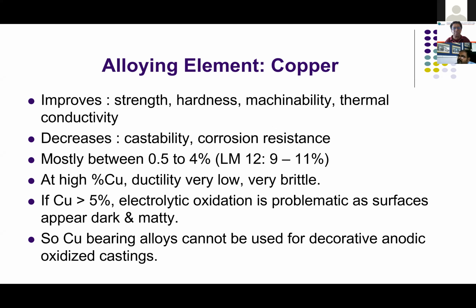Copper is a metal. Now, copper's melting point is much higher, but still at 750 degrees centigrade, copper is added to liquid aluminum. It dissolves like ice going into lemon juice, or salt going into water. When you maintain aluminum around 750 degrees centigrade, you add copper in the form of small ingots or small piglets, or copper wire or copper scrap. It goes into solution beautifully. It dissolves very well. So dissolving copper is not a major issue.